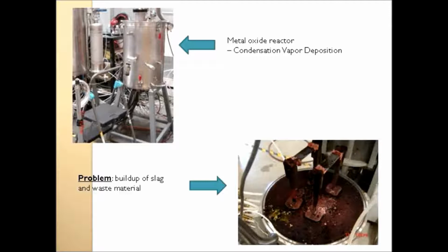We found during the initial assessment that the material was just being dispersed everywhere. Every sample that I took was positive for their materials of interest. So I recommended using a local exhaust ventilation. This is getting to a question that was raised earlier. We can talk about it more. This particular local exhaust ventilation is used in the welding industry. It's a fume extractor, and welders put it on the workbench as they're welding, and it draws the fume away from them.